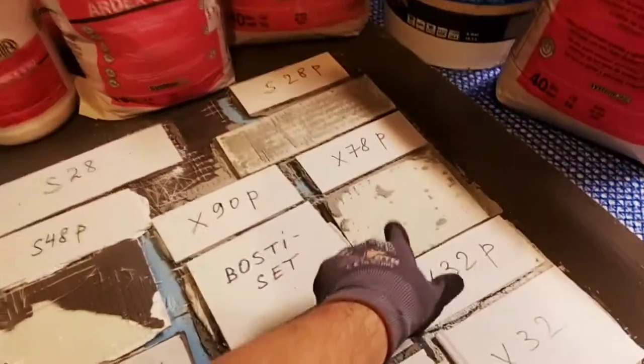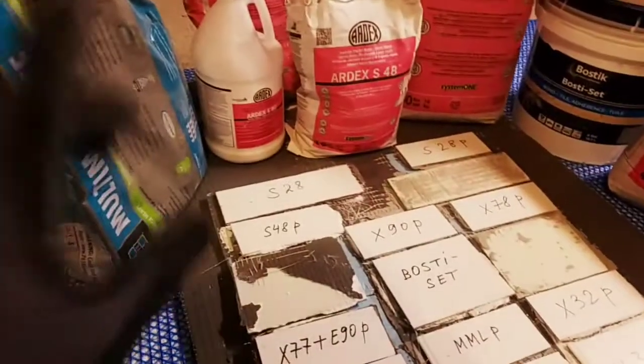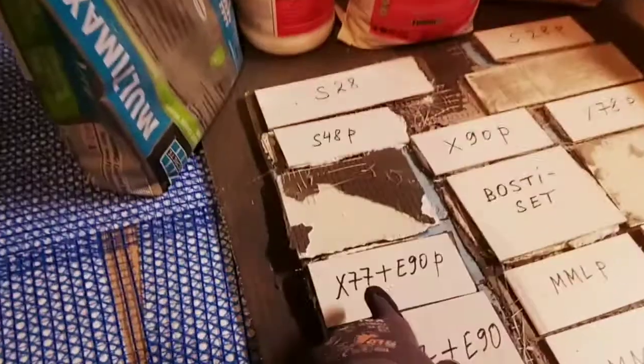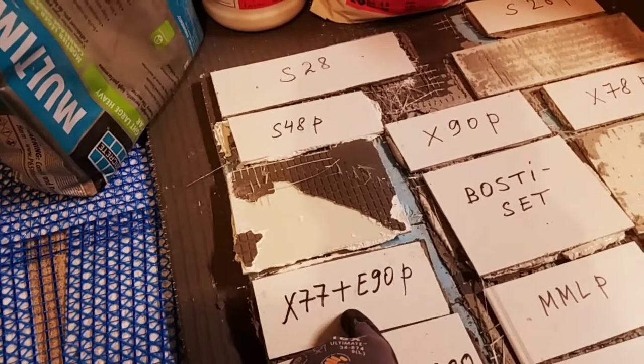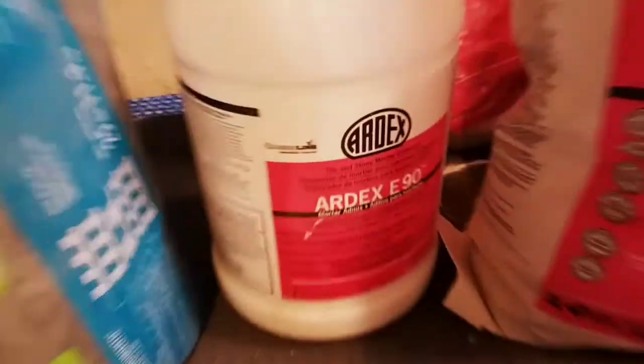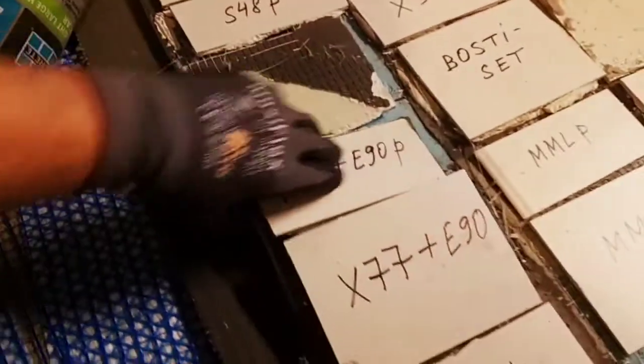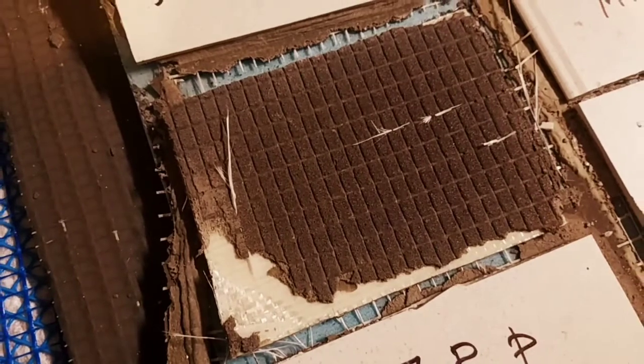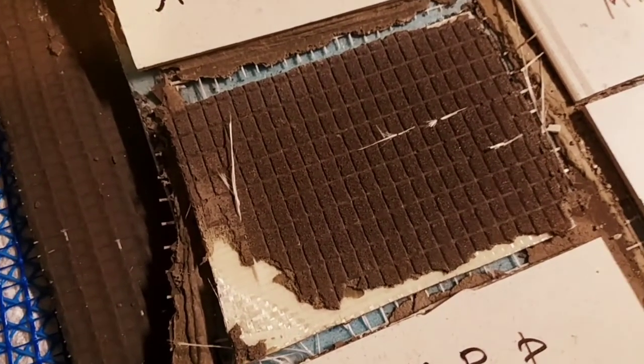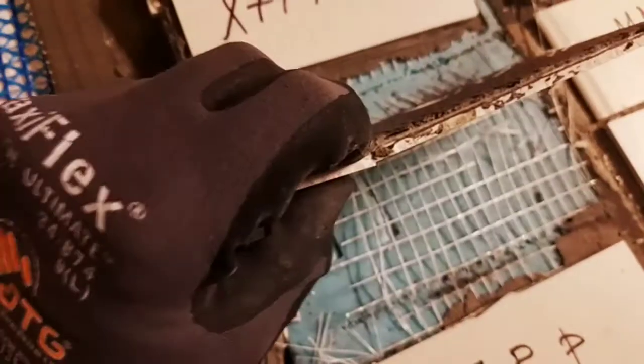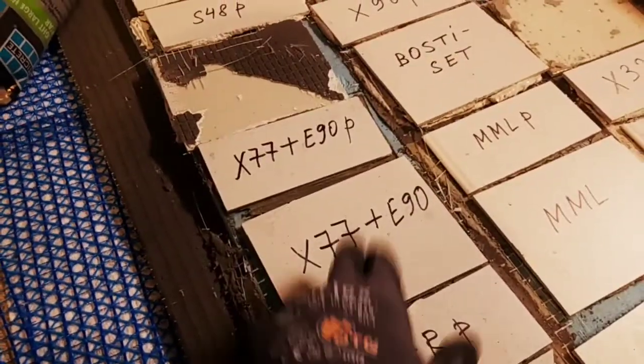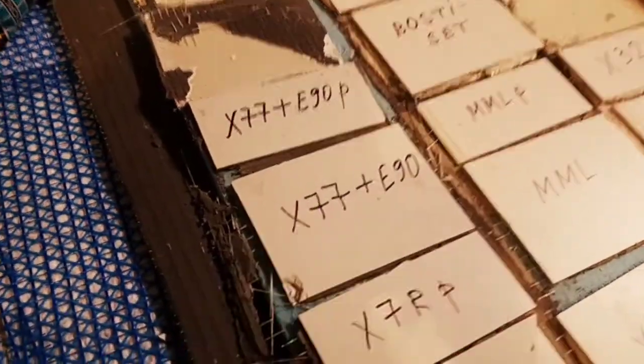Cosentino, which manufactures this product, Dekton, recommends using Ardex X77 mortar with Ardex E90 additive. And this is the result. Sorry, this was the primed version, this is unprimed. Well, as you can see, after 7 days, it showed very strong bond, very good adhesion to the back of this resin backing. And so we can see that whatever the manufacturer of Dekton recommends is true,